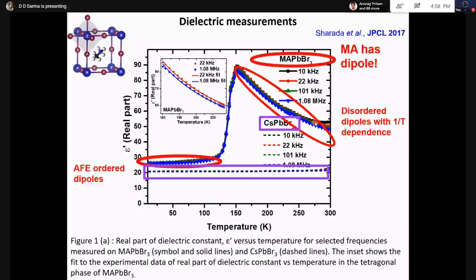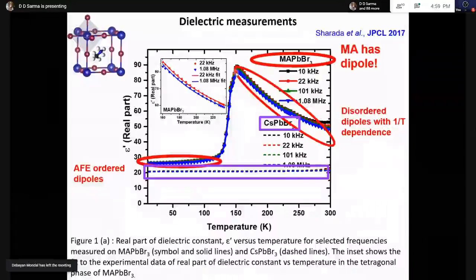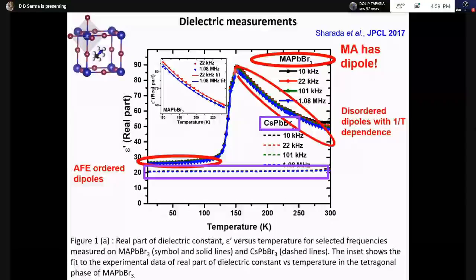In fact, one can in detail model this and fit this to find out the dipole moment and the rotation, and that is done over here, but those are technical aspects. I'll not go into that. But basically, this 1 over T dependency shows that the dipoles are freely rotating. Whenever one is freely rotating, one has to keep in mind what is the time scale I'm talking about. If anything is rotating at 1 second rotational speed, if you look at it with time scale of 1 year, it will look like freely rotating.